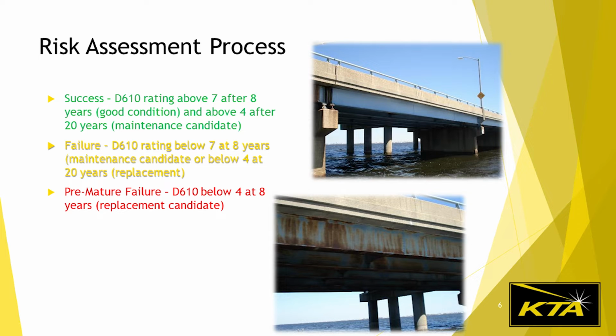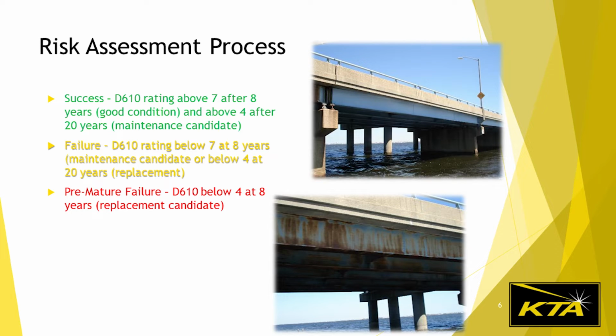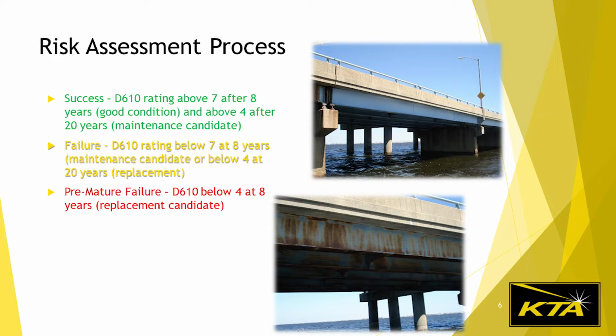Visual inspections were performed in 1995 and 2007 by Pete Alt. Each span was given a rating per ASTM D610. The standard essentially gives a rust grade from 10 to 0, with 10 being no rust, 0 being above 50%. The coating system was considered a success if it displayed a rating of above 7 after 8 years and above 4 after 20 years. These systems would be considered maintenance candidates. Failure was below 7 at 8 or below 4 at 20. These systems would be considered replacements. And a premature failure was anything below 4 at 8 years would also be a replacement.